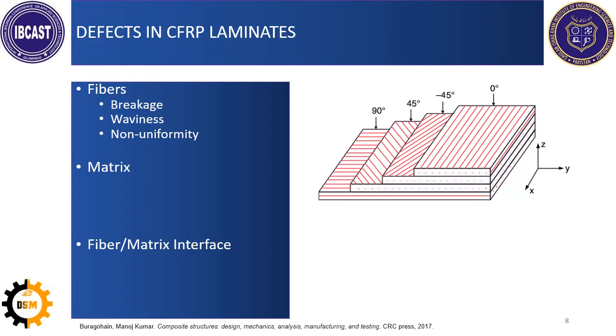Another fault can be the improper orientation. Improper orientation means that the micromechanics and macromechanics told you that your orientation should be exactly minus 45 degrees, but while doing your hand layup or your pre-preg layup process, you by mistake put them at minus 48 degrees. So the final properties of this composite material will differ from the one you designed it for. So this can result in a defect because the real loading conditions will be different from the one you designed it for. So this is another defect. These four types are the basic defects in fibers.